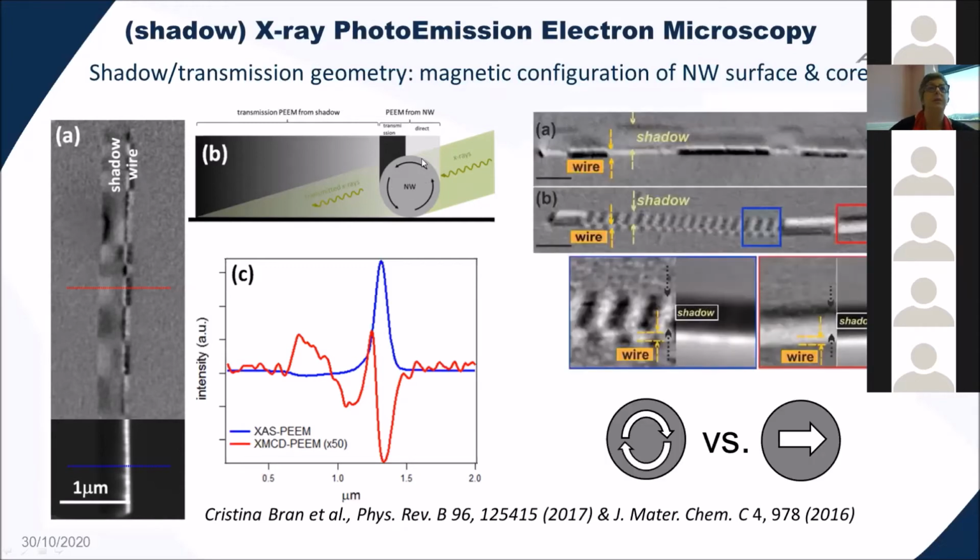And it's amazing what growers can do nowadays. For example, you can see that the aspect of the contrast in the shadow is very different when one has a curling magnetization or a transverse magnetization. So it's amazing that one can make this kind of wires with crystalline material where the crystalline anisotropy totally overcomes the shape anisotropy of a very, very elongated wire. No? One can also fabricate wires modulated in diameter, modulated in composition, etc., to imprint certain characteristics.